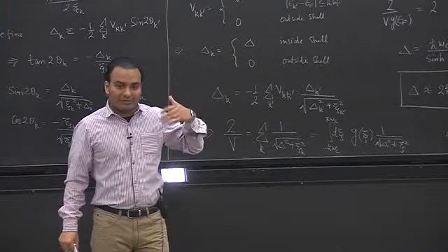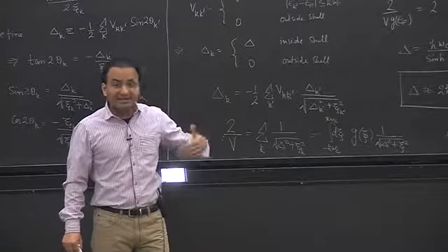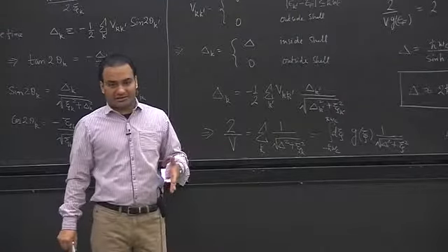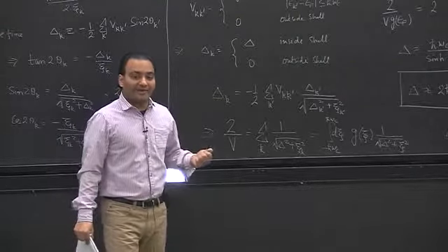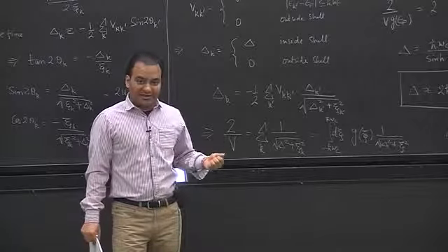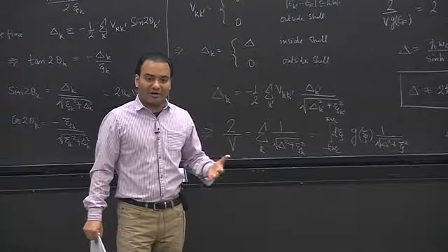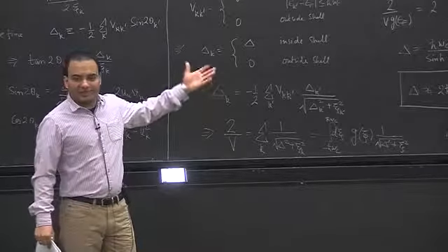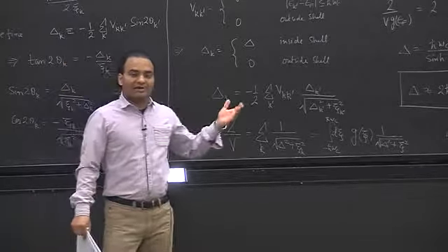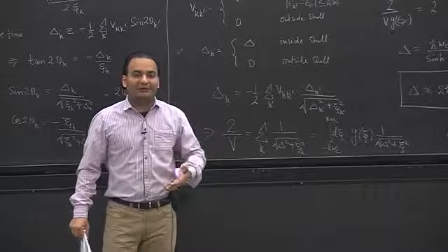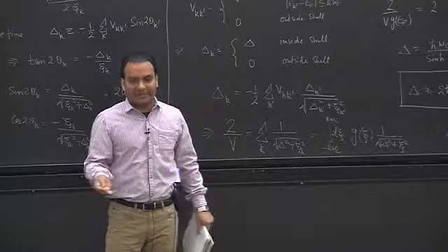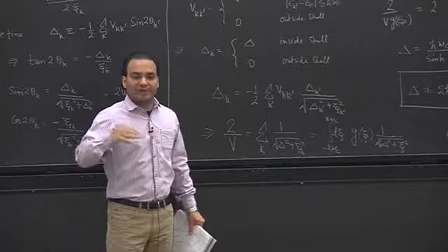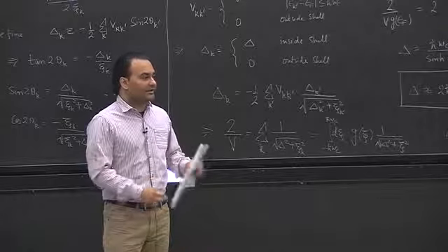But the reason that we assume there are attractive interactions is because of phonons. So we should keep in mind that this ħω_c is actually related to the phonon energy scale. I called it a new variable ħω_c because its relation with the Debye frequency involves some other factors. But you can think of this ω_c as really the Debye frequency, some energy scale of the order of the Debye frequency.